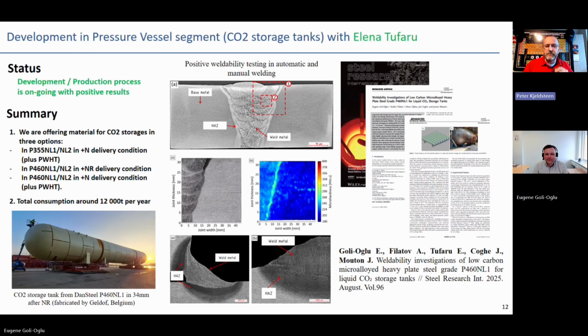And the microalloying with niobium, vanadium, is that to remove the carbon to make very small inclusions of carbides? Or is it to make fine-grained homogeneous material? Depending on the technology. For example, in case of as-rolled technology, addition of vanadium will work like a strengthening element, creating nitrides and carbides of vanadium, depending on content and equilibrium, and will reinforce the steel, I would say, with dots, which are carbides and nitrides of vanadium. But in case of normalizing or TM plus ACC, niobium, and less so but still vanadium, will make better grain refinement.